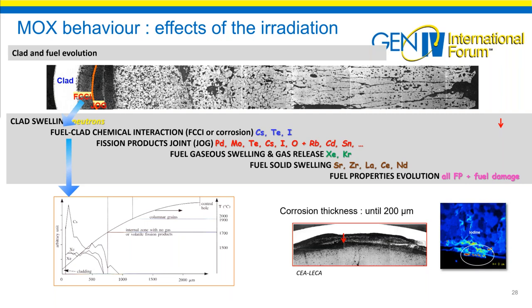So the evaluation of such a corrosion by some fission products can be done through thermodynamic studies of the interface between the fuel and the clad. We have to say that the temperature threshold for the corrosion attack on the cladding is around 500 degrees, but it's also depending on the fuel, as I said, and especially on the stoichiometry. The maximum value seen is 200 microns, which represents 40% of the clad thickness. So you can expect performance reductions due to the risk of failure with a thinner clad, submitted to pressure and creep, that could have a risk of failure only due to this corrosion. So next slide, please.